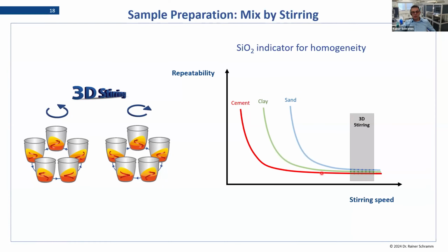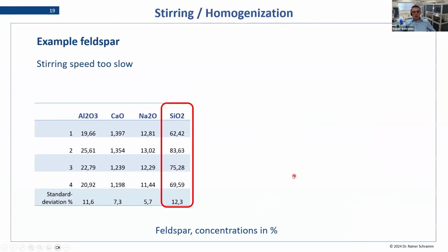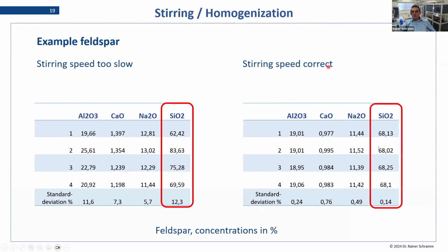So this is a very good indication, and I just indicated here that of course different samples with different dilutions need a different agitation. And I have here an example of feldspar, which is sometimes difficult to fuse, and here you see if the speed is correct, we have a very small standard deviation. If the speed is not correct, we have a very high standard deviation. So very easy to find out. And then you can optimize by increasing your speed or increasing your dilution of the sample until you have a very low standard deviation. And then you are sure that your agitation is working correctly.